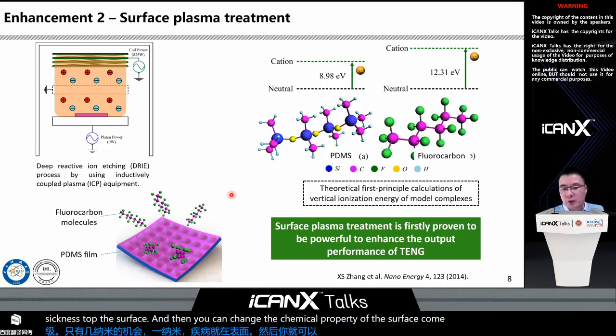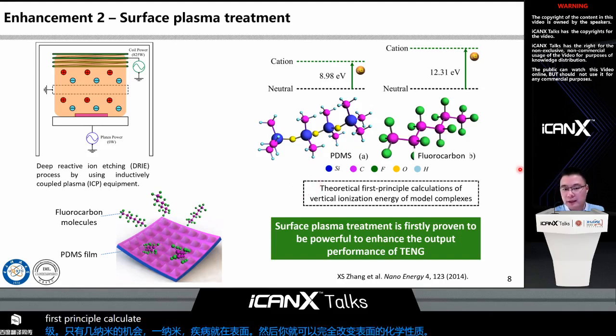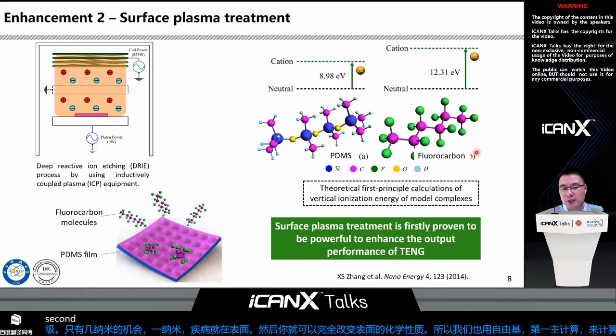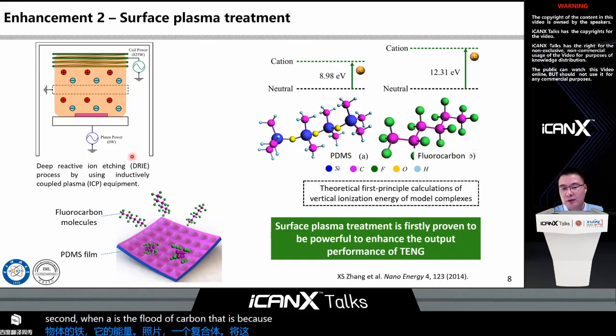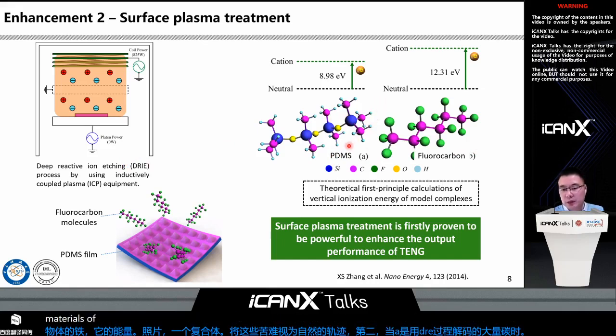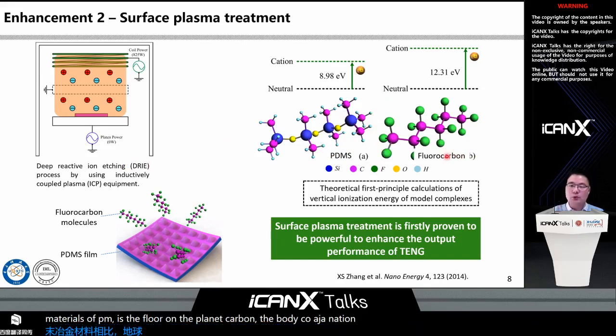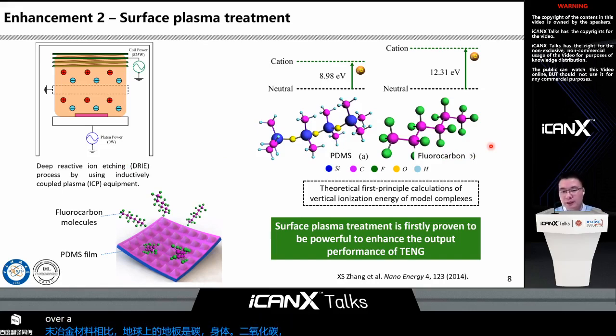So we also used theoretical first principle calculations to calculate the vertical ionization energy of the model complexes. One is the PDMS, that is the conventional material to construct this triboelectric nanogenerator, and the second one is the fluorocarbon that is deposited by using the DRIE process. So we found that compared with the traditional material, the PDMS, the vertical ionization energy of the fluorocarbon can go up to over 12 eV, and for the PDMS it's only about 9 eV.